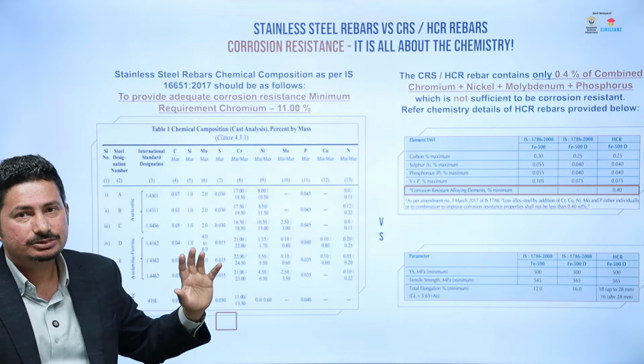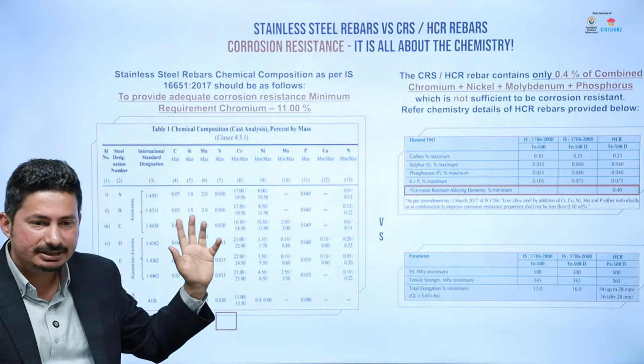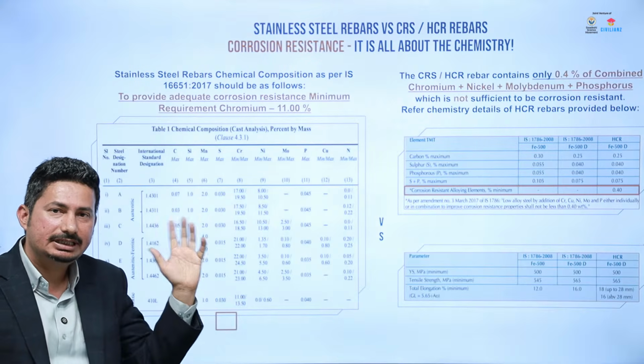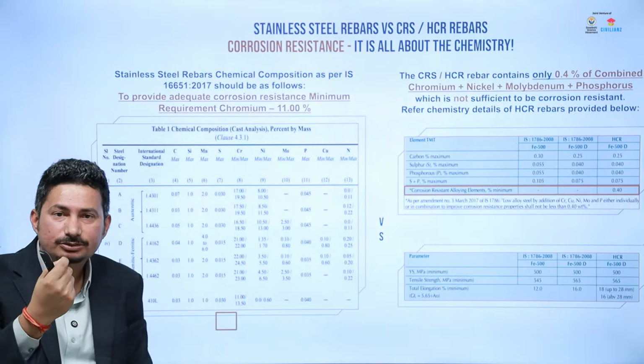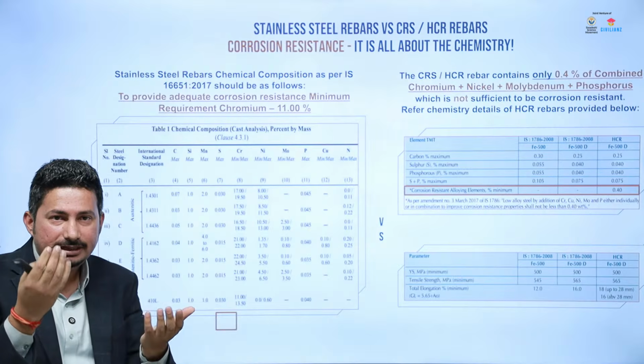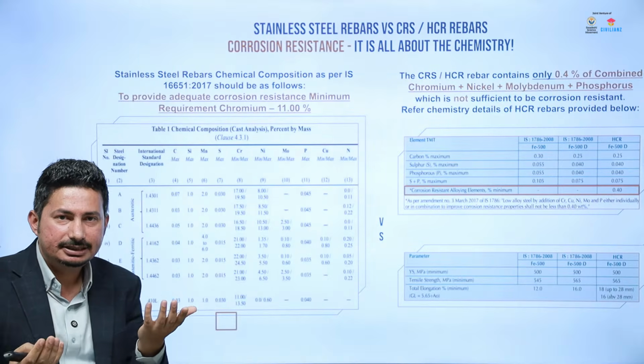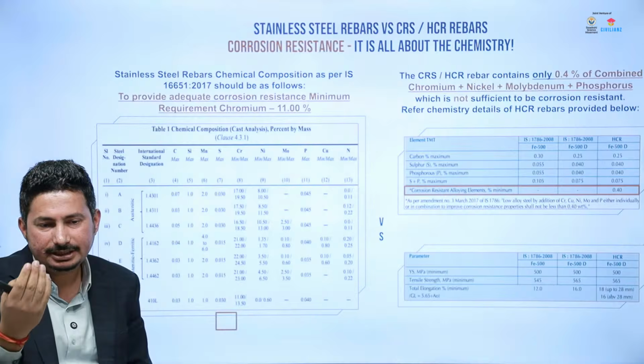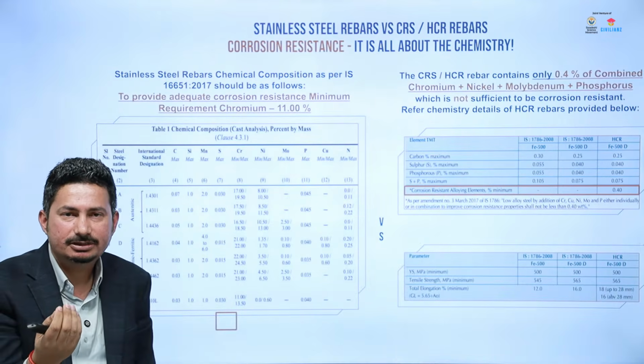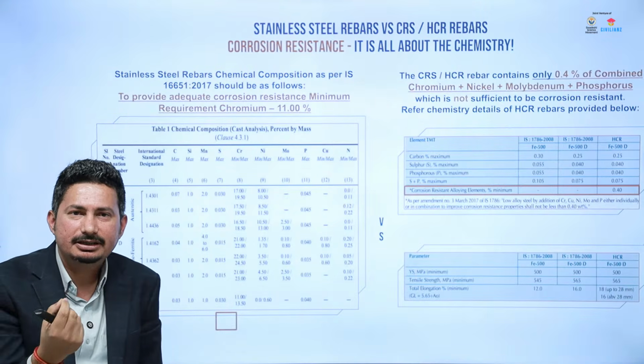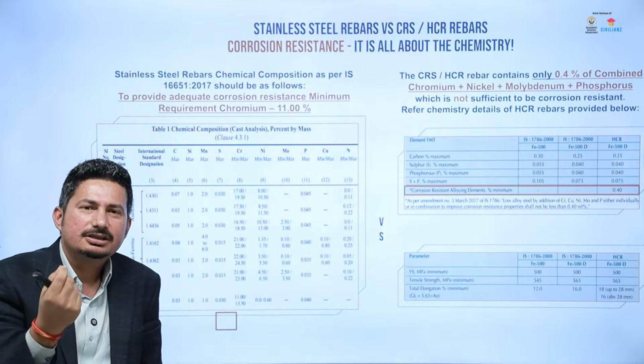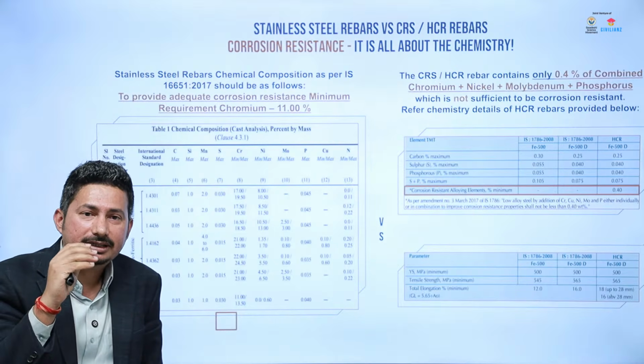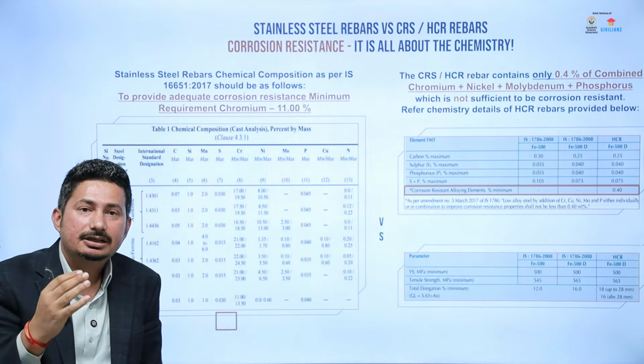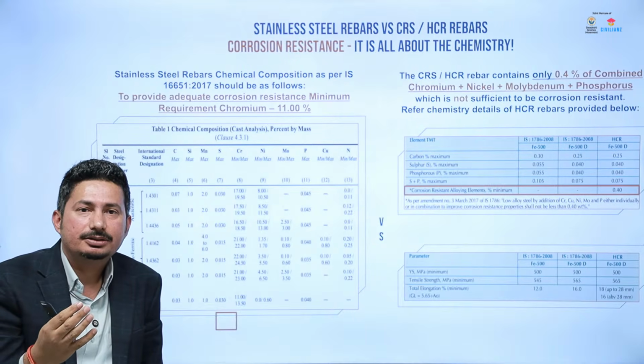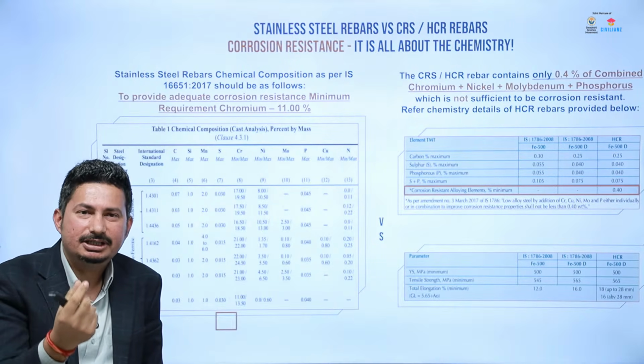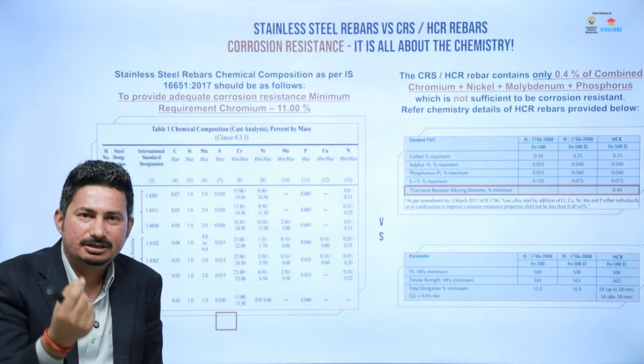As we discussed in the previous slides, when we talk about stainless steel rebar, a minimum of 10.5% chromium should be there. So the chemistry itself is so different: CRS rebar has only 0.4% of corrosion resistant element, and chromium in it is mostly 0.02 or something like that. Because of that, the real efficacy against corrosion may not happen, because of the very limited corrosion resistant element being present in that.